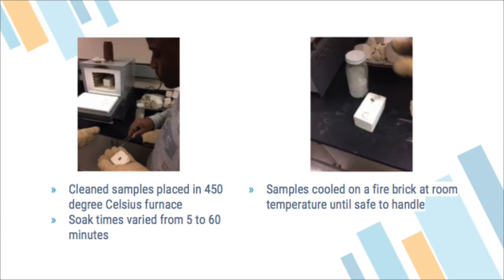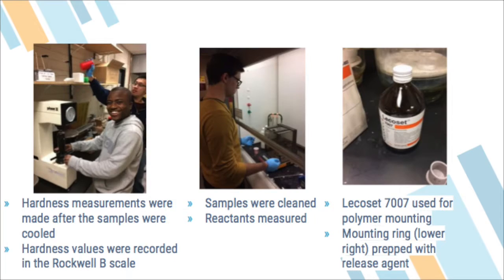The samples were then removed in series as their soak times expired. The samples were allowed to cool on a fire brick at room temperature until they were cool enough to handle without protective gloves. Once the samples were cool, the hardness of each sample was tested using the indenter method. All measurements were recorded using the Rockwell B scale. The samples were then cleaned and prepared for mounting in epoxy.